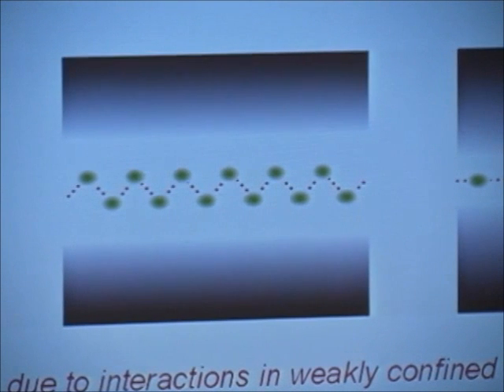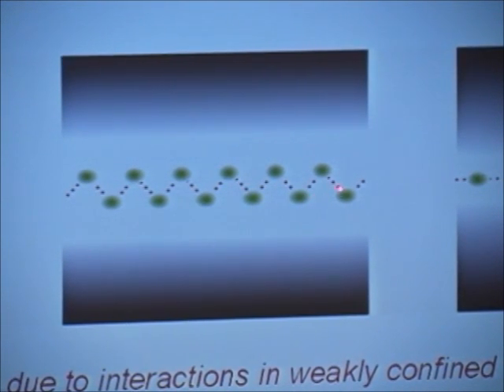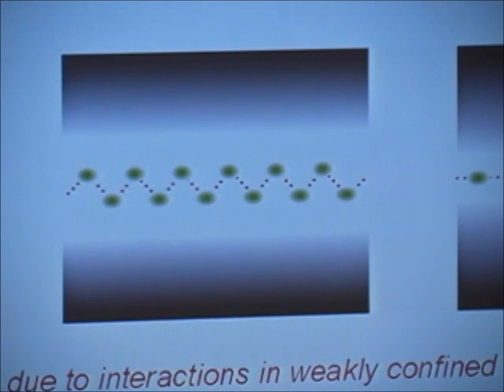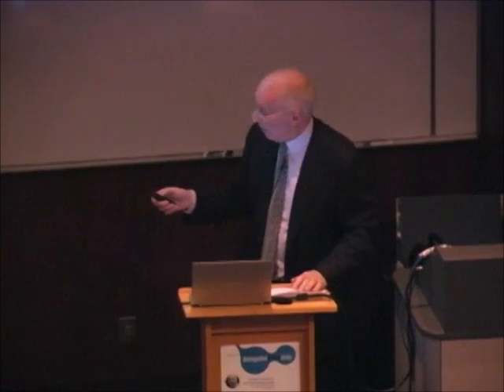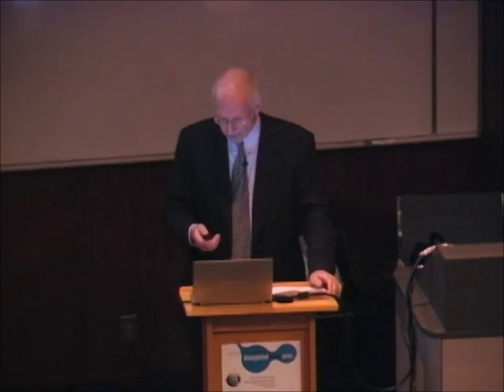And that's what happens. You start to get a zigzag pattern like that. One of the more interesting features, as the zigzag develops, is that this electron can be nearer this one than that one. In other words, what was previously its second nearest neighbor becomes its nearest neighbor. Now, as we further relax the confinement potential, so it's almost flat, this zigzag will split up into 2 distinct lines. And that is an incipient lattice. In other words, the electron gas is now starting to form the precursor to a full lattice. In a sense, the 2 lines, or rows, is a lattice, but it's basically moving towards a full-blown two-dimensional lattice.